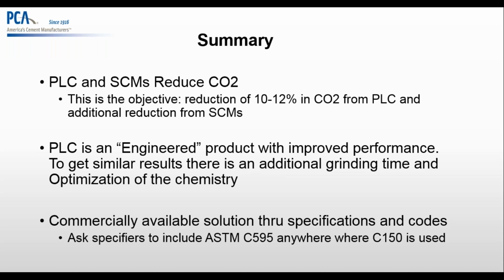So PLC is an engineered product with improved performance. The cement manufacturers need additional grinding time in order to produce this PLC, and there needs to be an optimization of the chemistry. Otherwise, it will not perform as determined. So the ASTM C595, please do not forget that, because there are already commercially available solutions through the specifications.